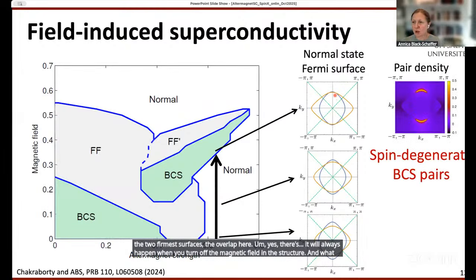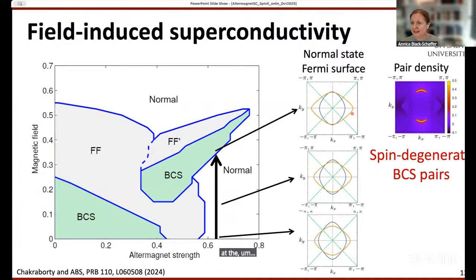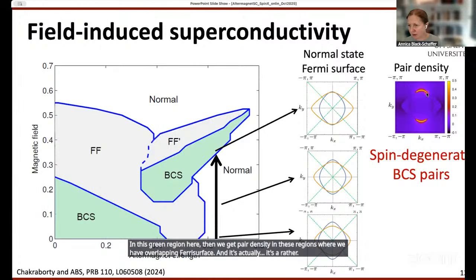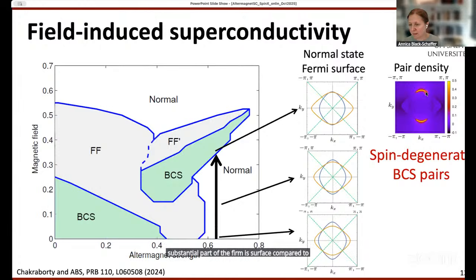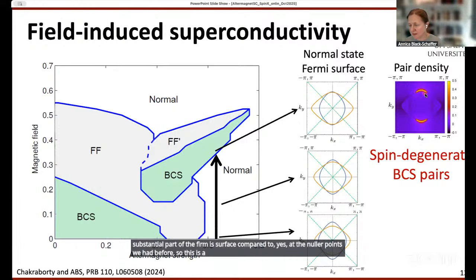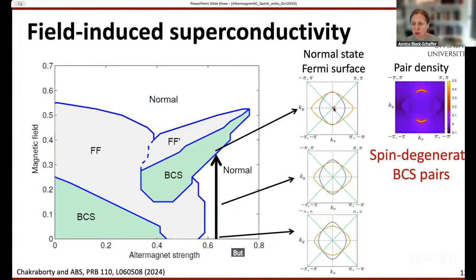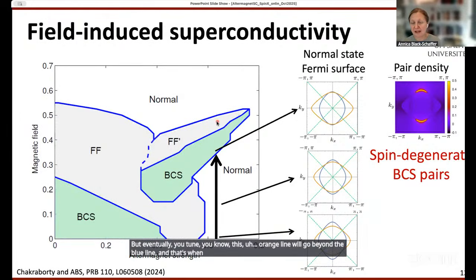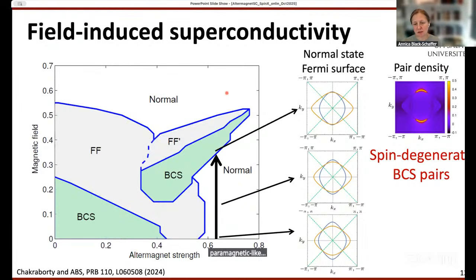And what happens then, if you look at where the pair density is, is that exactly in this green region here we get pair density, in these regions where we have overlapping Fermi surfaces. And it's a rather substantial part of the Fermi surface compared to just the nodal points we had before. So this is a reasonably stable BCS regime here. But eventually as you tune, this orange line will go beyond the blue line, and that's when you enter the FF phase, and eventually it's so much a paramagnetic-like structure that it goes into the normal state.